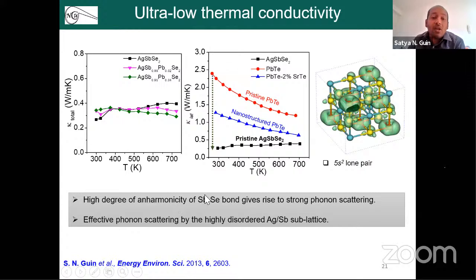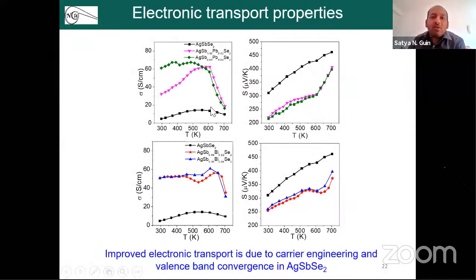So this is because of the high anharmonicity of the bonding, and you have a very special atomic arrangement, like a disordered atomic arrangement in the system, which results in very low thermal conductivity of the material. Furthermore, we studied the electrical conductivity and the Seebeck measurements, which show a very high improvement in the electrical conductivity after doping with lead and bismuth in the system.